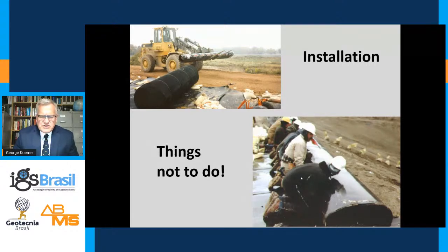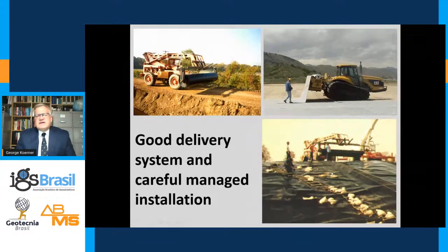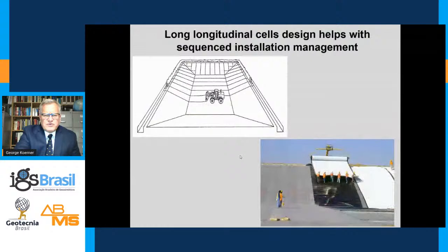This is a smooth geomembrane. The roll is extremely heavy, and they're about to throw it down the side slope in a very uncontrolled manner. This is totally unacceptable and certainly is not the way to do it. Good delivery systems are shown here. This is typically equipment, a lull with an articulating boom and a spreader bar. This is equipment which is operated remotely. There's a toggle, and the installer is here walking in back, making sure the overlap is correct. But this is certainly carefully managed and controlled throughout the system.